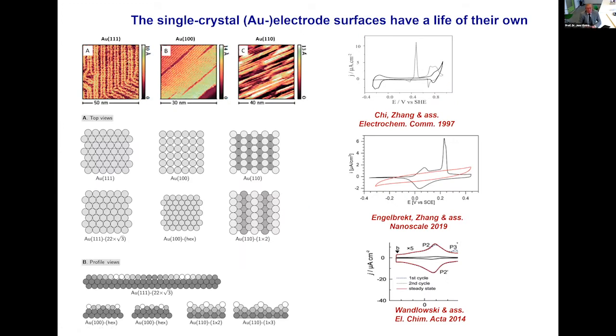If we begin with a clean electrode and gradually work our way up, so to speak, from a single, let's call it 0 dimensions, up to 3 dimensions, then this is what the single crystal gold electrodes look like, the 3 low index facets. This is what they look like schematically from above and from the side. You will see that you can actually see single atoms.